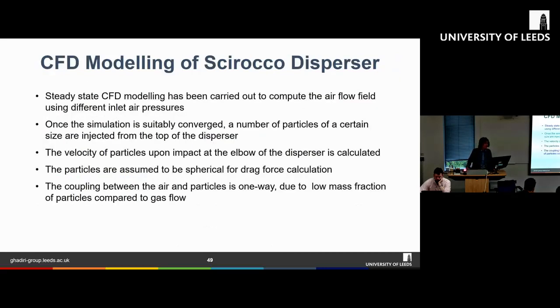And of course, to use Ghadiri's model, we need to have an idea of the impact velocities of these particles when they are inside the system. Unfortunately, with the setup of the Malvern Mastersizer 2000, we can't actually measure the impact velocity by using a high-speed camera or anything like that. So the way we can characterize or predict the impact velocity is by CFD modeling.